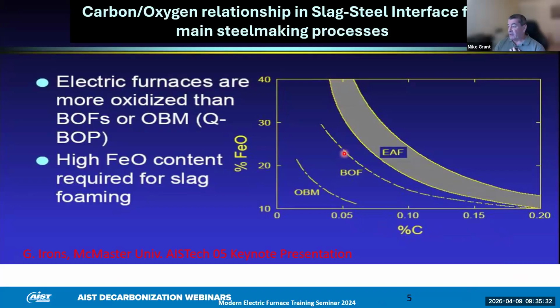the slag. It's less for the BOF and even less for the bottom blowing because these two vessels mix the steel much more rigorously. And so there's not the gradients that you have in the electric arc furnace, where all the energy is going in at the top. You're heating up the top with oxygen and with the arc, and so there's very little convection taking place. So you have cold, high carbon steel at the bottom and very low carbon, high oxygen steel at the top, coupled with a slag, which produces a high FeO slag, and this is yield loss. And why I'm showing this diagram, of course, is because it plays into some of the assumptions I make later on.